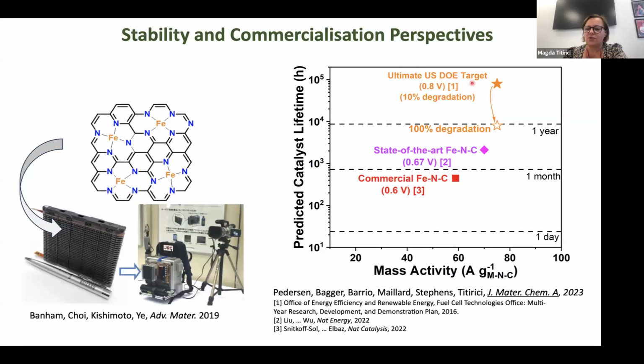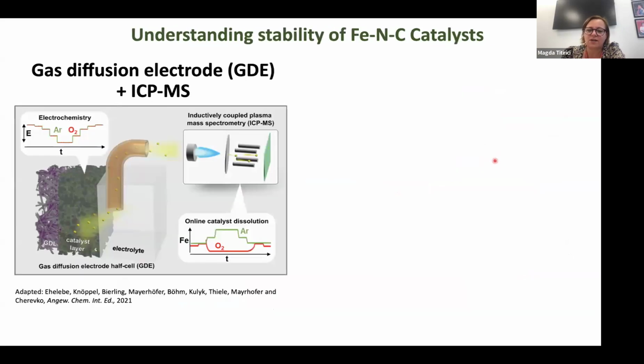So that's the DOE target that you have. You need to have a catalyst in your fuel cell that would last more than 1 year. And normally for the commercial iron nitrogen catalyst, they last less than a month. There's only one commercial catalyst, and the best reported in the literature degrades in about, I don't know, 3 months, let's say. So this is not very good.